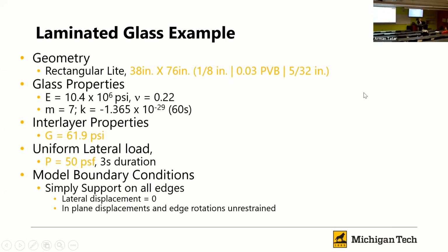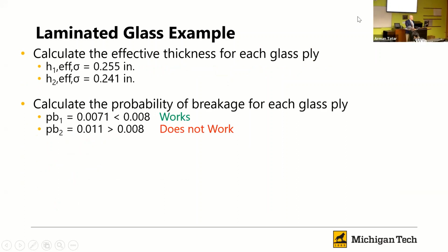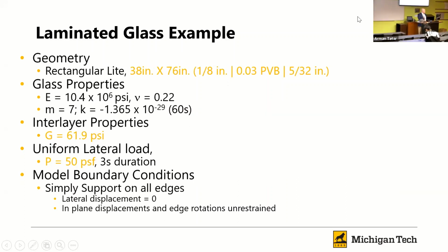So if I wanted to repeat this process with laminated glass, something we need to know is what our laminated construction is. Here I'm using an asymmetric construction because I can. The rectangular dimensions are the same, and we have the thickness of our interlayer, and we have a material, in this case PVB, and for the shear modulus for PVB I used about 62 PSI. Oop, I went too far. Last thing is that I'm going to check this for 50 PSF, not an uncommon design wind load for windows.